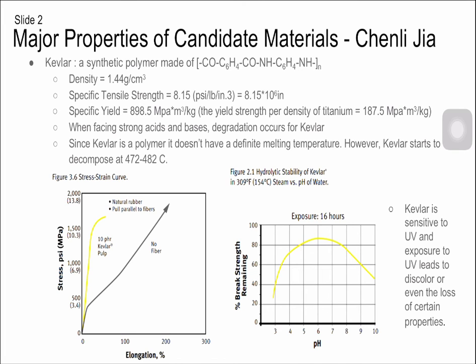However, Kevlar is not very good at dealing with strong acids and bases. When facing strong acids and bases, degradation occurs for Kevlar. You can see that from figure 2.1. Since Kevlar is a polymer, it doesn't have a definite melting temperature. However, Kevlar starts to decompose at 472 to 482 degrees C. Just like most polymers, Kevlar is very sensitive to UV light, and excess exposure to UV light leads to discoloration or even the loss of certain mechanical properties for Kevlar.